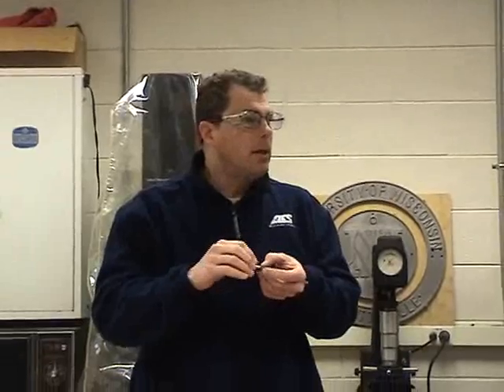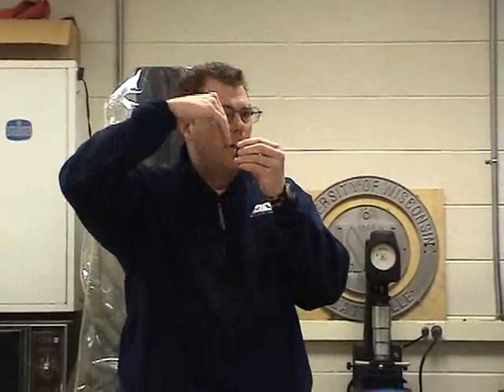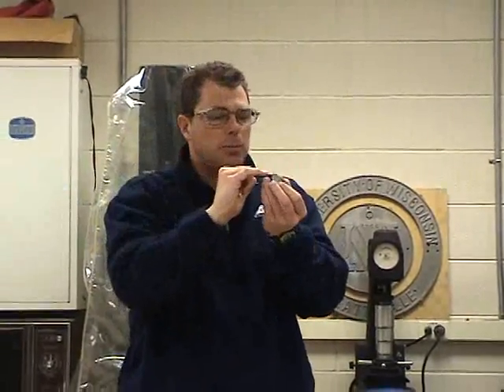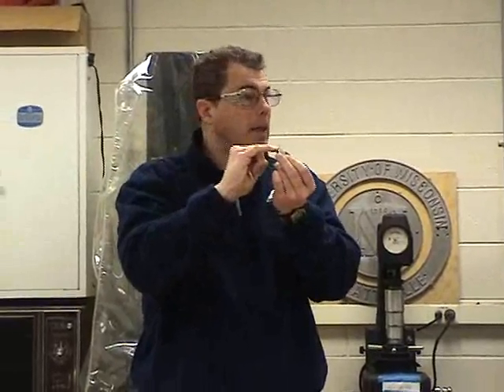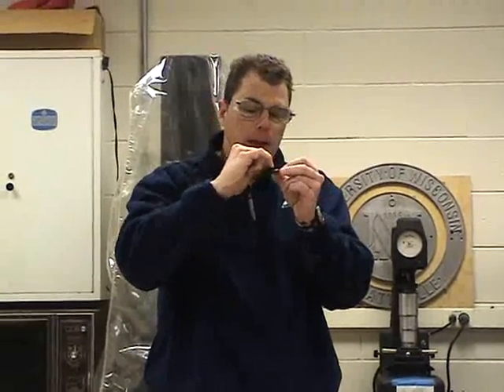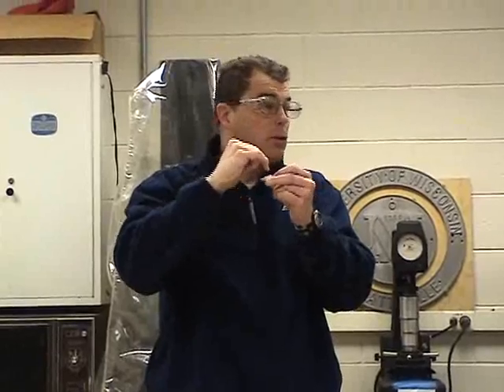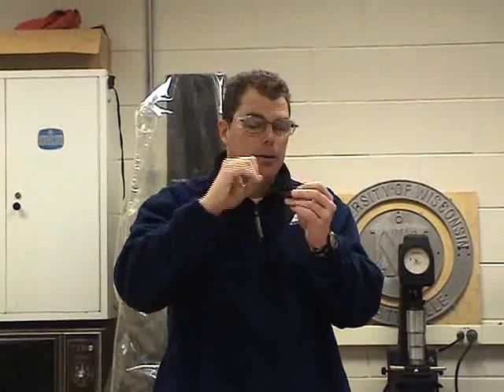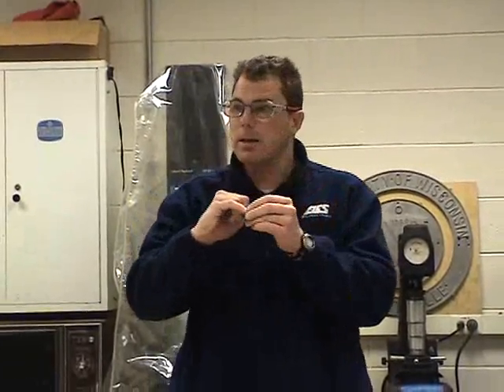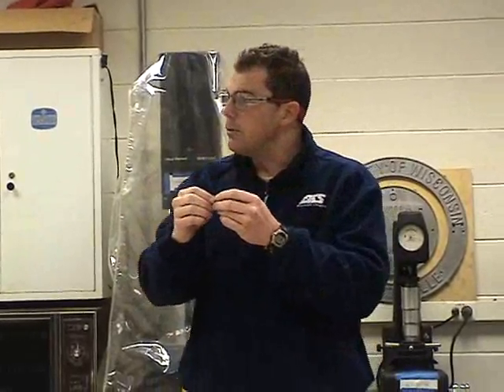Unfortunately, as it cuts through the bottom side of the part, it gets really thin there, and it's hard for the coolant to get down there. So this little burr that's left on the edge will probably be fairly hard, and possibly some of the steel right around it. So you don't want to drill your hole there, and you don't want to take a hardness there, because it might give you a wrong reading.